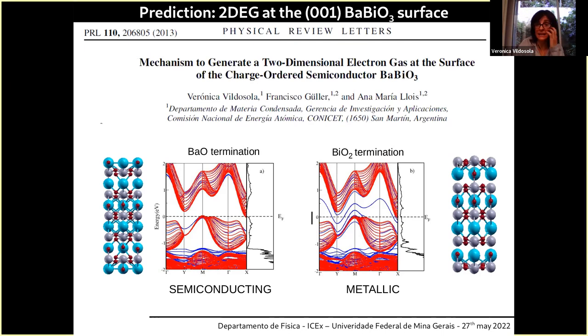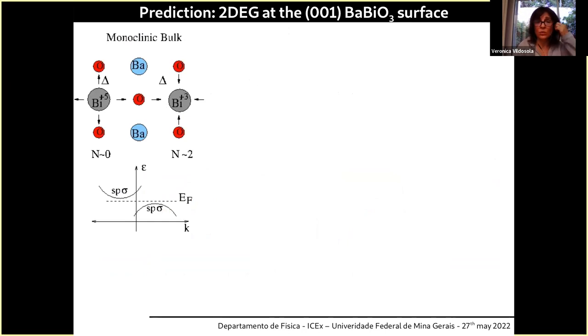But when we study the surface terminated in bismuth oxygen, some metallic surface states appear in the band structure. We tried to understand phenomenologically what was going on, and here you see a cartoon of the monoclinic bulk situation where you have a bismuth 5+ giving charge to the surroundings, and each bond has some delta amount of carriers, and the bismuth 3+ receiving that charge from the surroundings. Here you have an empty band above the Fermi level, and here you have a full band that you can think about like a Wannier function centered around this ion 3+, a full Wannier function with two electrons, right?